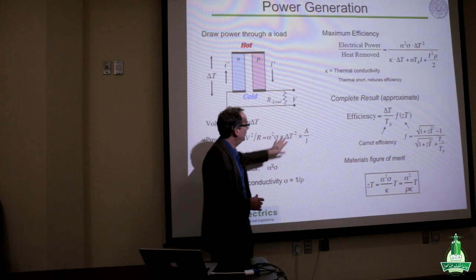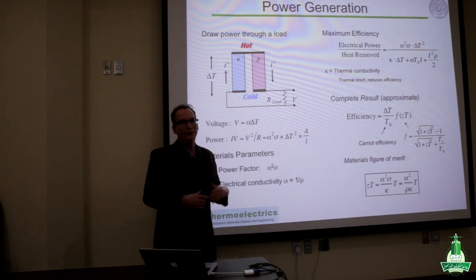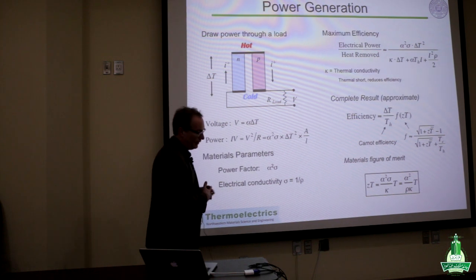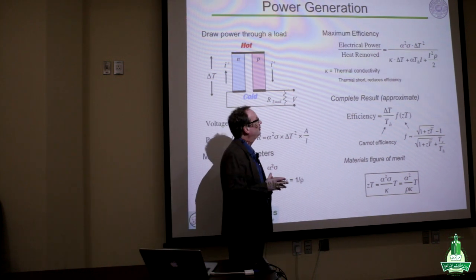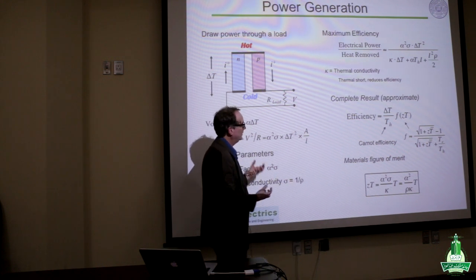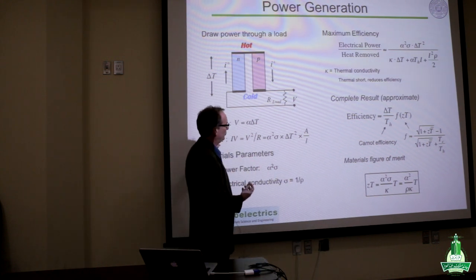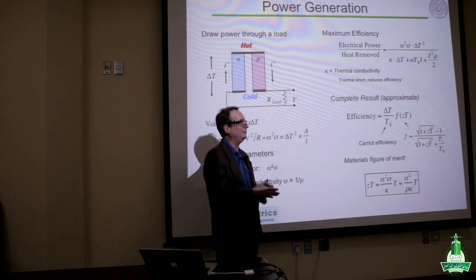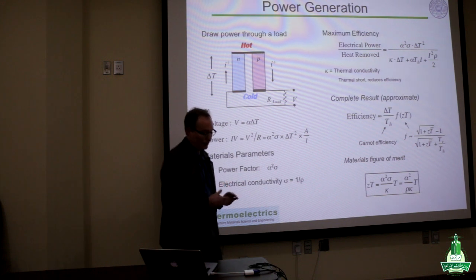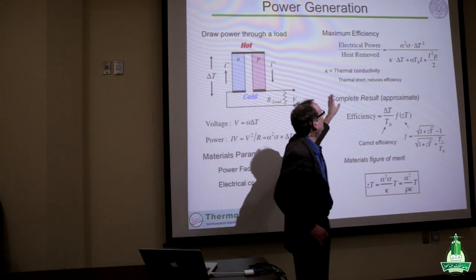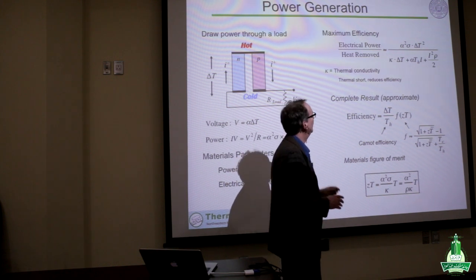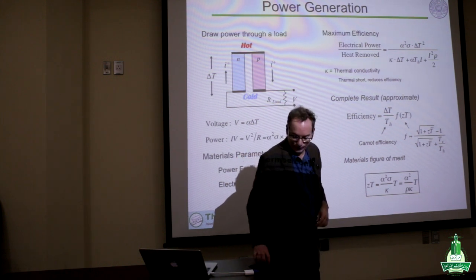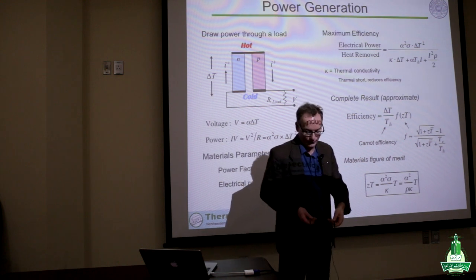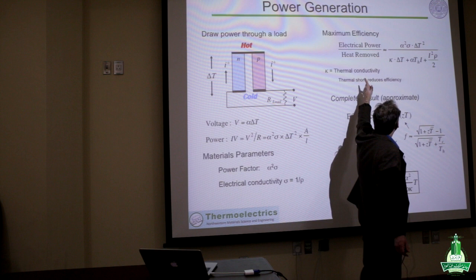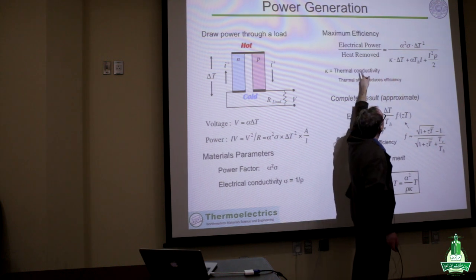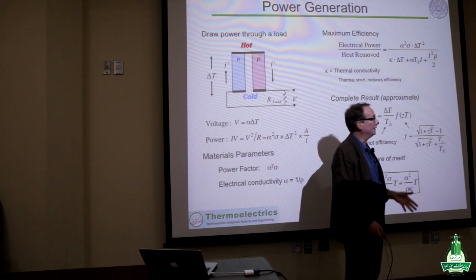And it turns out that for optimization, we actually want an efficient system. We want our heat engine to work as efficiently as possible, because in a system design, the true power comes from the efficiency times the heat flow through the system. So in thermoelectrics then, the real figure of merit is going to determine the efficiency rather than the power. And the most important parameter that gets added to this problem is the thermal conductivity, because it comes in through how much heat is removed in the system.